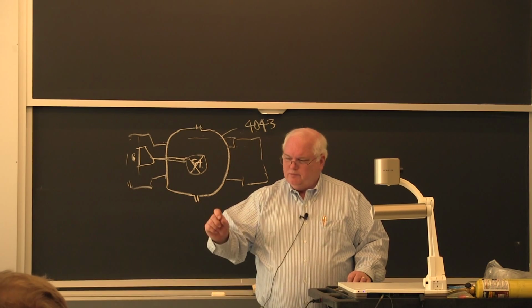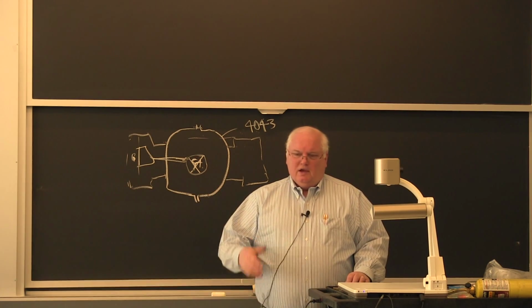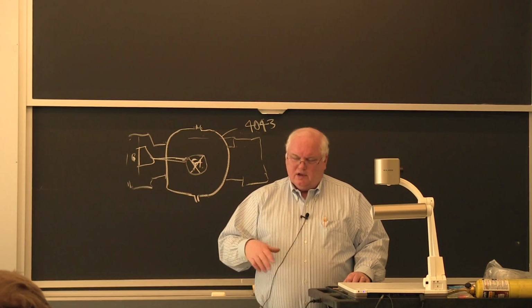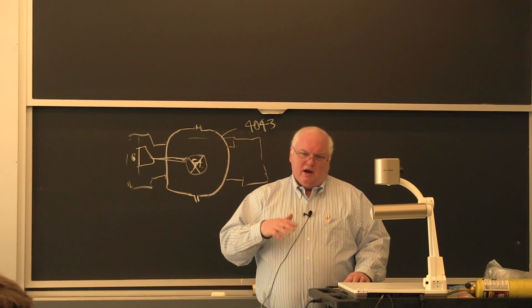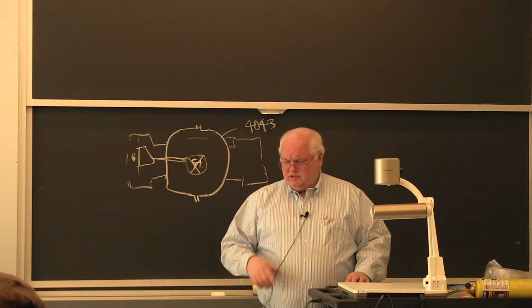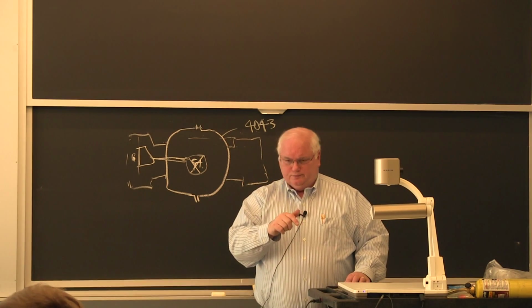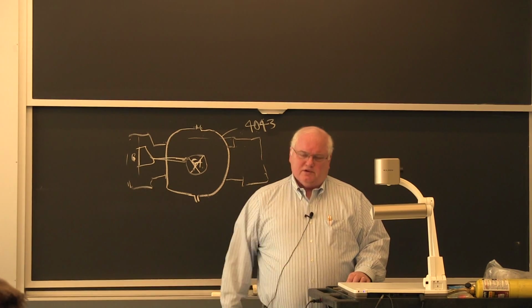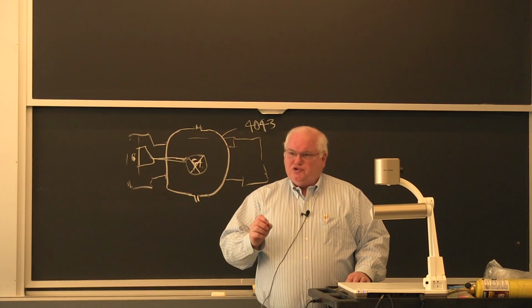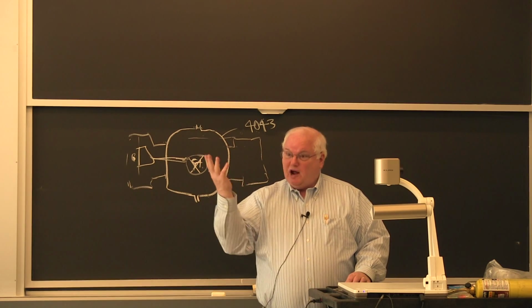I said, well, you make some little discs of aluminum, you go get them anodized to different thicknesses, and I talked to him about how many microns thick. So he goes out and he gets things anodized 4, 6, 8, and 10 microns. We come back, I find a laser somewhere here at MIT, and we basically hit each one of them with a pulse of laser energy, I think from a YAG laser, and we just measure the temperature rise of each little disc, and you can figure out how much was absorbed.